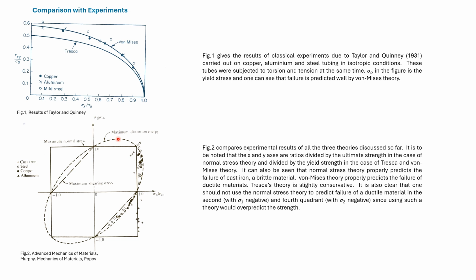As we can see, the von Mises theory correctly predicts the yield failure of the ductile materials, and Tresca's theory gives conservative results. Cast iron failure results are correctly predicted by the maximum normal stress theory. Also see here that in the second and the fourth quadrant, one should not use the maximum normal stress criteria to predict the strength of ductile material, since the maximum normal stress theory will overpredict the strength.